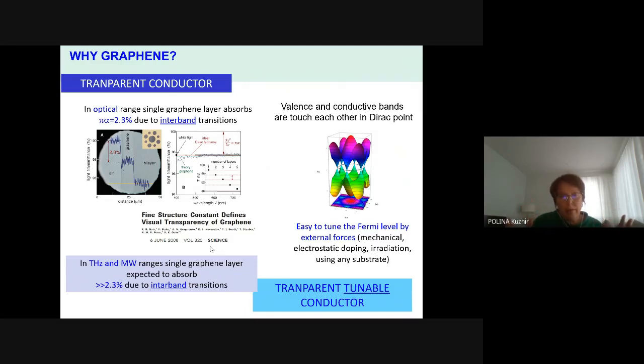So why graphene? Because it is highly absorptive, even in the optical frequency range, and we could expect that it will be absorptive, and much more absorptive, in the terahertz and microwave frequency range. But also, it's very easy to tune the electromagnetic response of graphene because its electronic structure is composed such a way that the valence and conductive band touch each other.